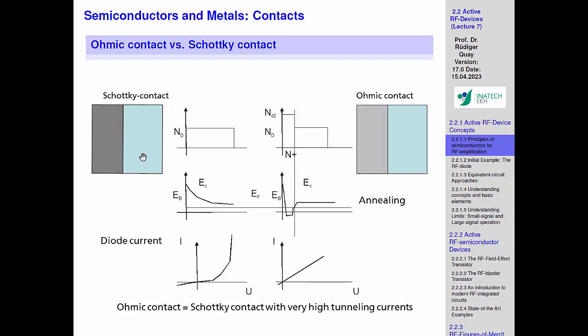Yeah? And then from this picture you can understand why people put doping, because what you can do now, which is depicted on the right, instead of just putting the metal on top, you first dope the semiconductor and then put the metal on top. Because if there would automatically be a region which would be highly depleted, but if you put many carriers there, which is what we are doing by doping, then you bend this, it's still pinned up here, but you make this layer so thin by doping that everything tunnels through.